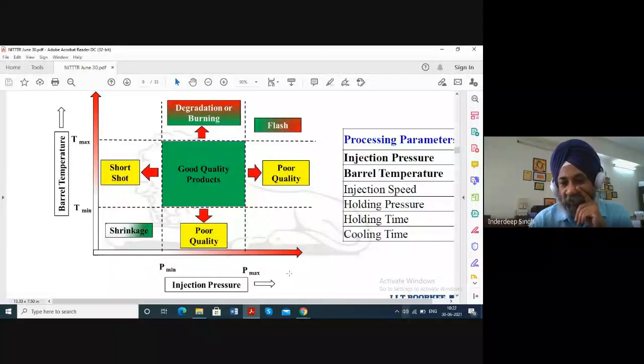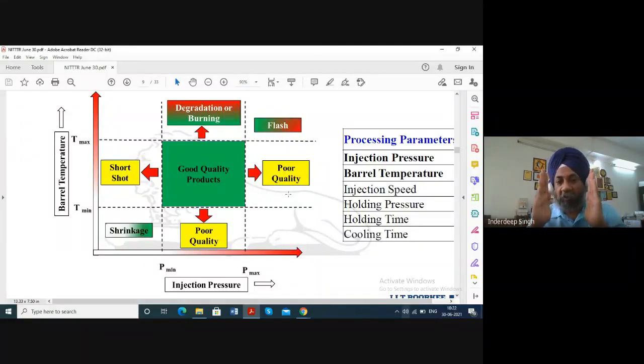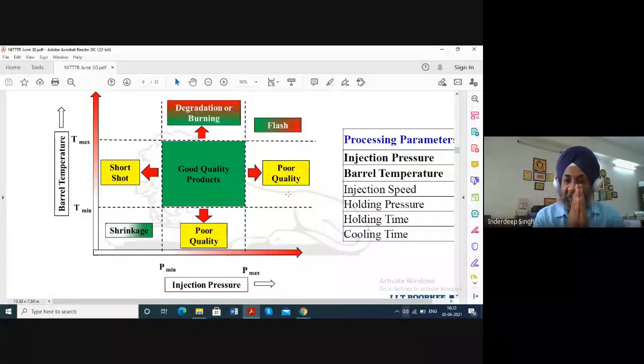Similarly, with injection pressure, if it is too high, there may be flash, where the material comes out from the area where the two molds are closing. The mold is open like this, it closes, and the flash may be seen at the closing points of the plane in which the two mold halves are closing.